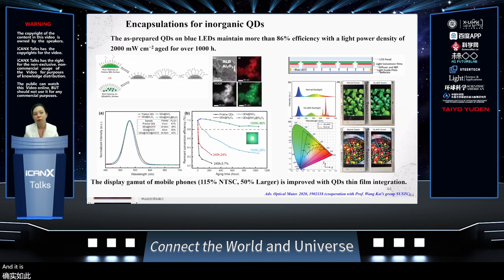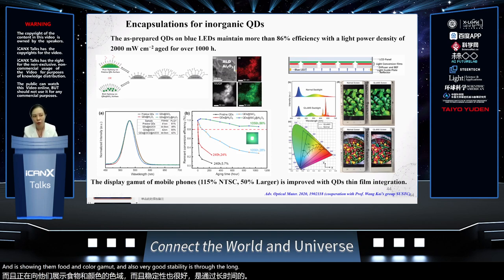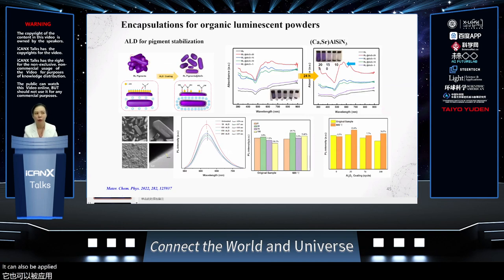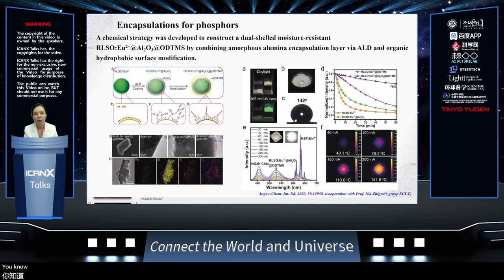And it is not only for the perovskite quantum dots, it's also good for this kind of lead type or indium phosphide type of quantum dots. We actually adopt this technology and also integrate it in the phone, and it's showing a good color gamut and also very good stability through long usage. It can also be applied for organic luminescent powders, like the violet pigment. It helps to enhance the color of the pigment. And it has also been utilized for phosphor encapsulation.